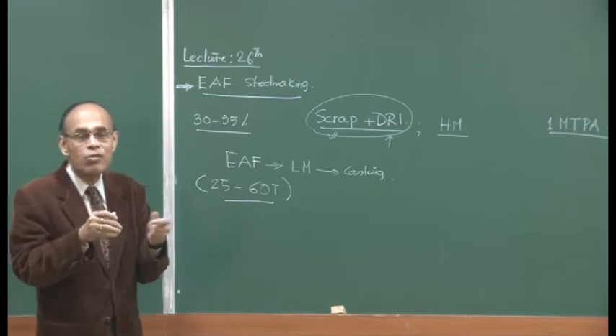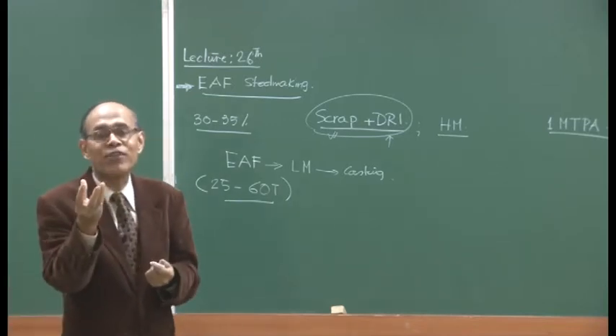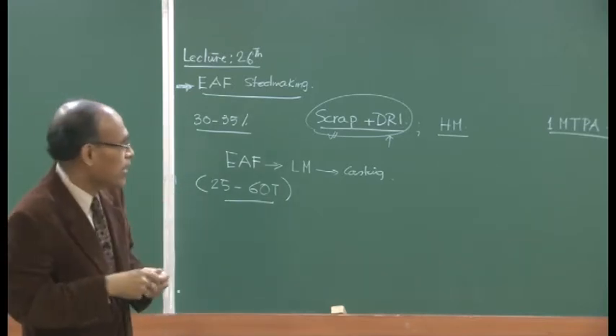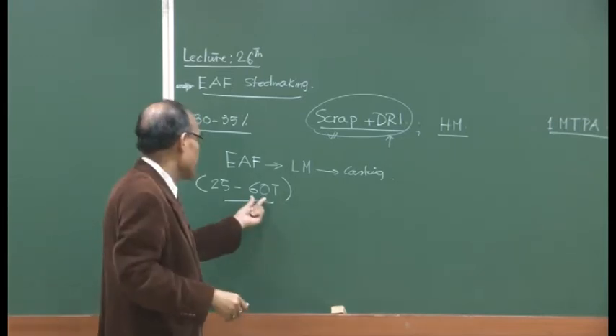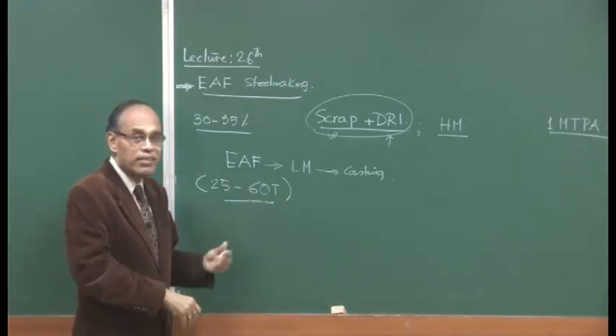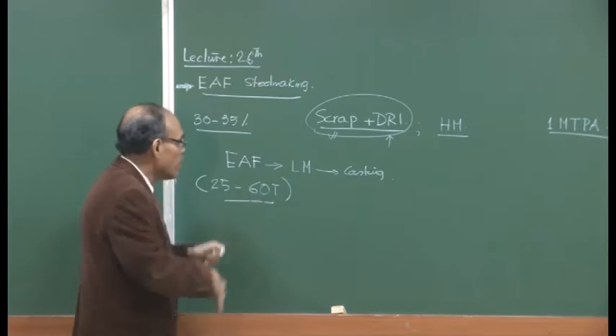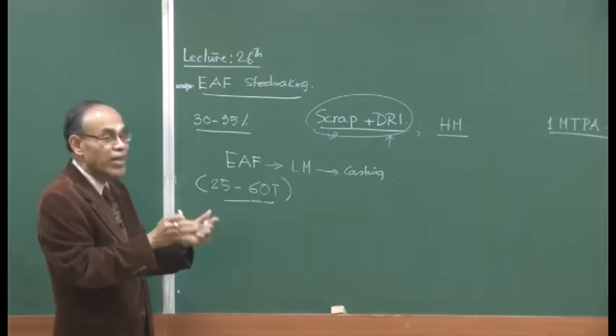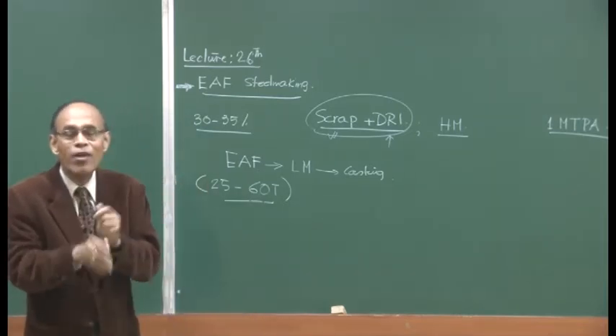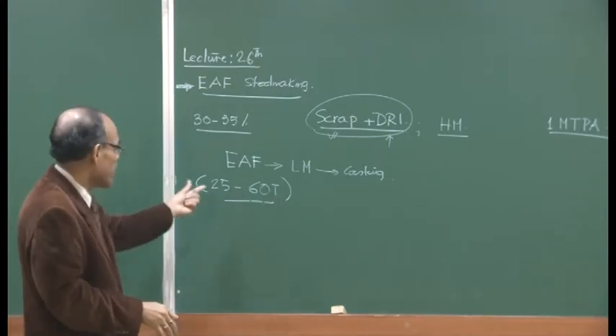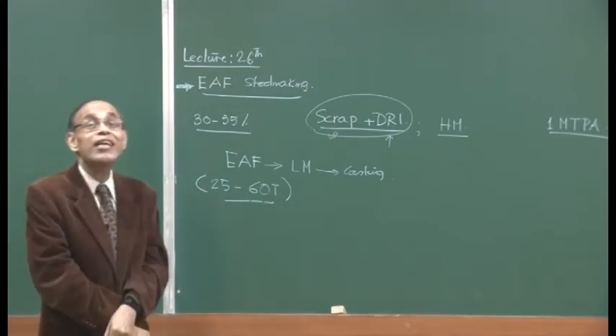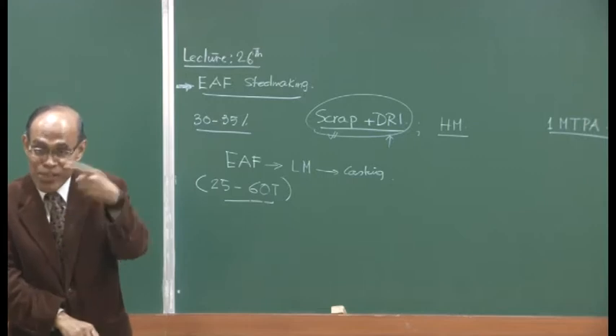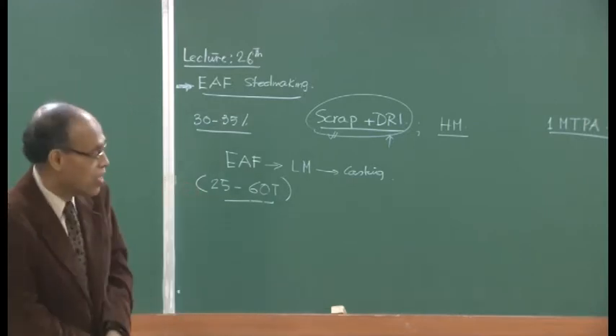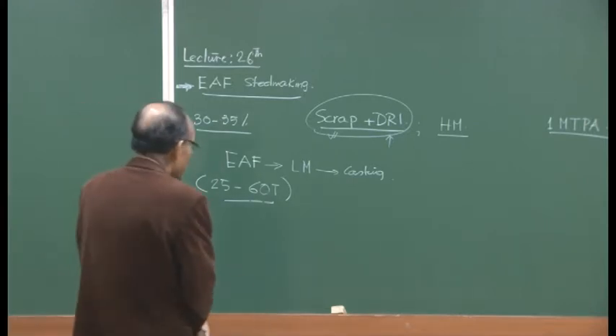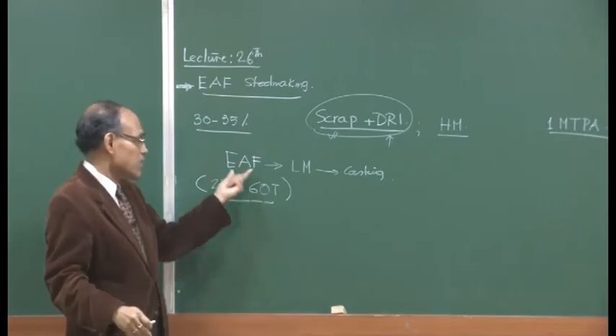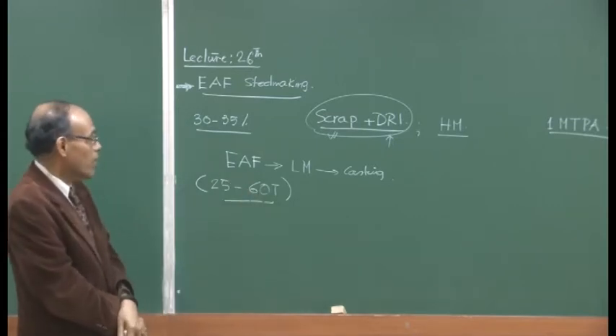For many of these steel plants, you do not require, for example, automotive gears of a certain size at the level of 200 tons or 300 tons, something like that. So, that is why these furnaces are pretty small, because the customer requirement, the heat size requirement or the volume requirement remains small. But in the case of plain carbon steel production, if you go to JSPL Raigarh or to ArcelorMittal Nippon Steel in Hazira, the size of the arc furnaces tends to be much bigger.